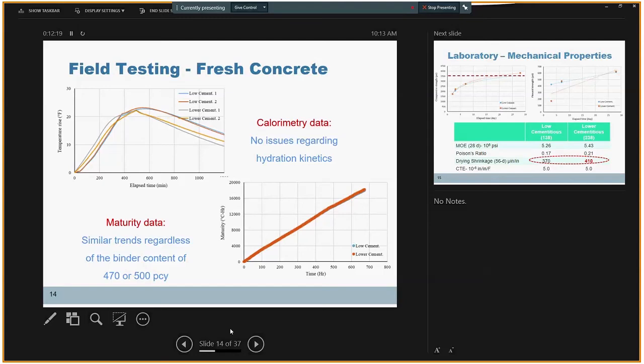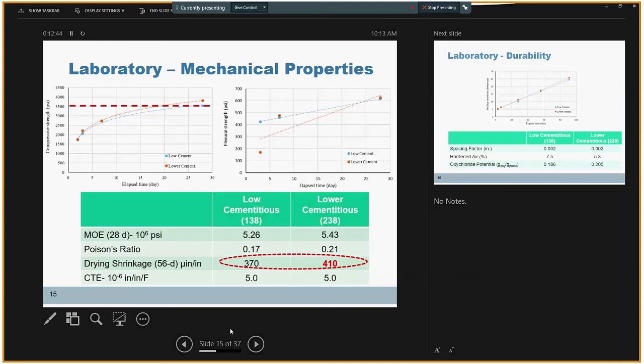No problems like that. And also the maturity data we got from the sensors were totally similar for both concrete types, regardless of the binder content. The figure at the bottom of this slide shows the maturity data. We see the data is almost overlapping over time for these two concrete mixtures. The maturity data was also verified by compressive strength development. Especially at early age, both concrete types present comparable strength values, and both concrete mixtures reached the minimum of 3,500 psi at 28 days.